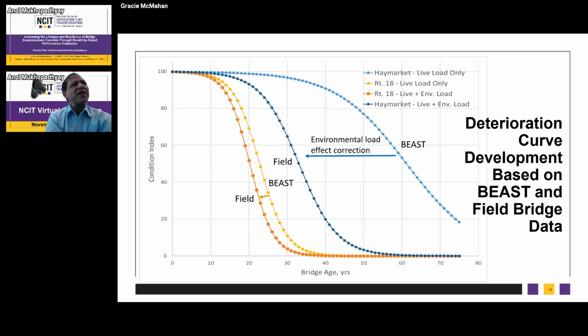This is a very interesting slide. That's probably the most important slide here. You see here the blue curve, the BEAST curve. BEAST did a 2-year study in accelerated condition. Now they try to predict under field conditions for a particular bridge like the Haymarket Bridge, applying the ADT values, and they try to predict the load-only deterioration curve, called BEAST, the blue curve. And then for the environmental loading effect correction, they went to the field, spent almost 6 years on NDT evaluation, and they developed the field curve.